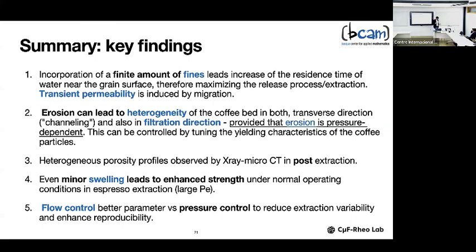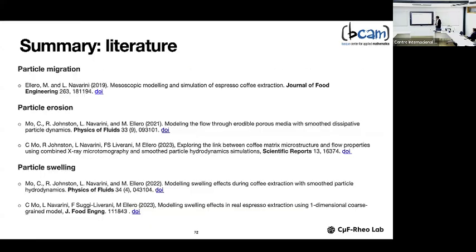Even a minor amount of swelling, of the order of 3%, can alter dramatically the flow rate in a highly packed coffee bed, and therefore produce, again, an increase in strength. And finally, when you compare pressure control to flow control, of course, flow control in the end will try to rule out all the possible unknowns which come from different microstructural effects, therefore controlling essentially the residence time of a liquid at the solid-liquid interface, which in the end is the important aspect to promote the transfer of mass. And therefore, here there is some literature on the three different topics that we discussed today.